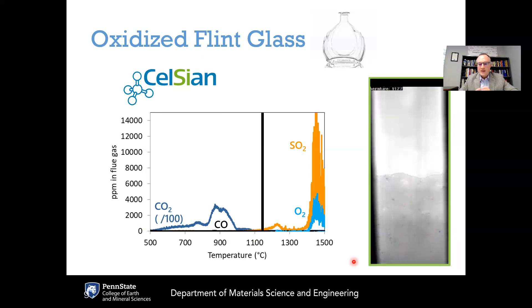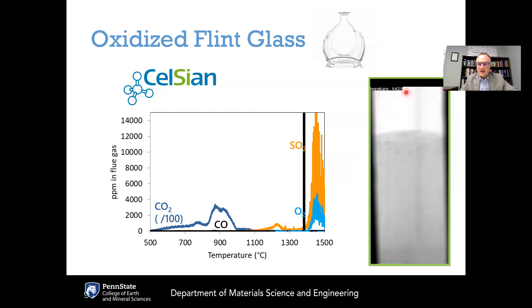Looking at the melting video: at 1200 degrees C you can see a lot of batch reactions taking place. Carbon dioxide has been released but there's still more needed to obtain a good quality homogeneous melt. At 1350 degrees C more bubbling starts. At 1400 degrees C the fining agents kick in, producing a foaming behavior as more gases are released, rising to the top and creating a homogeneous mixture. By 1525 degrees C all gases have been released and there's a high quality homogeneous soda lime melt at the bottom.